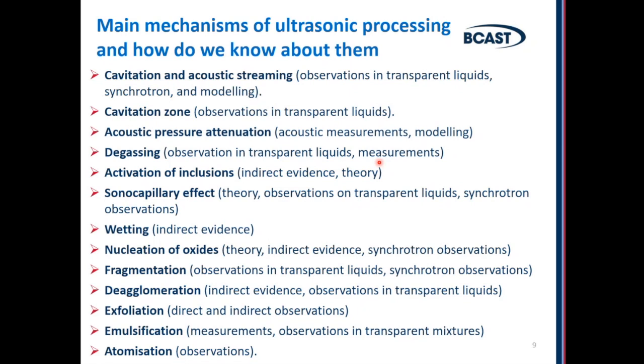There is a sonocapillary effect: under conditions of cavitation, liquid can penetrate into much smaller openings, for example, crevices at the surface or small openings in the filter. So much smaller capillaries, and that's called the sonocapillary effect. So cavitation helps to overcome capillary pressure. Wetting I already mentioned. Also under conditions of cavitation, the nucleation of melts on inclusions is enhanced. Also, solid particles can be fragmented, deagglomerated, and exfoliated in the liquid under conditions of cavitation.